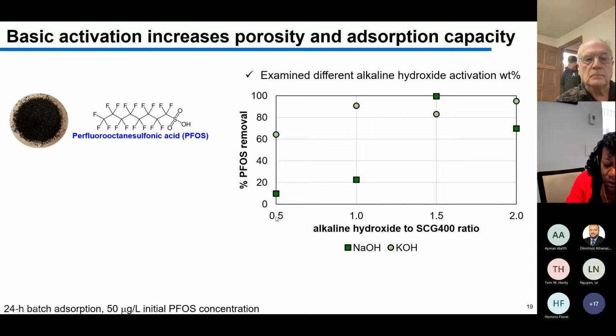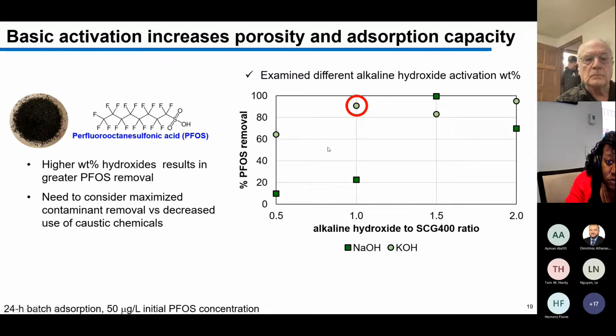So on the x-axis here, we're plotting the mass ratio of either sodium hydroxide or potassium hydroxide that we've added to grams of the spent coffee ground biochar pyrolyzed at 400 degrees Celsius, this SCG 400. So we can see that typically the higher mass dose of the activating agent that you add, the greater the PFOS removal. We decided to consider this 1 weight percent, so 1 gram of potassium hydroxide to 1 gram of the biochar material, to proceed with further testing because, again, we wanted to minimize both energy input and chemical input.